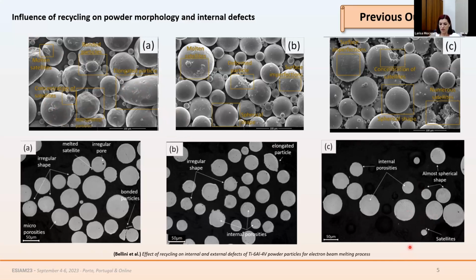Regarding the internal porosity, we saw that the virgin powders had a higher amount of internal porosity, and this is due to the gas entrapped in the particles themselves during the atomization process. And this tiny porosity inside the powder particles was decreased in the two recycled batches of powders, and this is probably due to the preheating inside the EBM chamber.